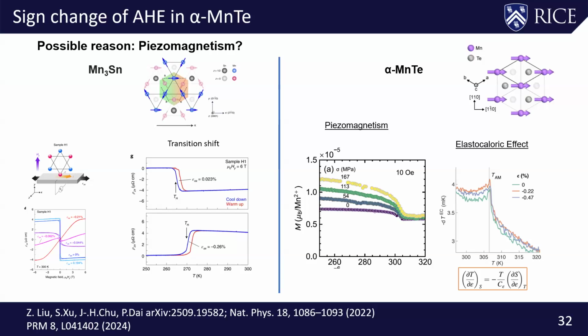Basically, due to the fact that you have a spin-lattice coupling, when you put a uniaxial pressure onto the system, you're changing the local symmetry, and therefore you change slightly the exchange coupling, and therefore you change the spin system. Therefore, the anomalous Hall is due purely to what we call piezomagnetism, because the magnetic structure changes slightly. Whereas in the case of alpha manganese tellurium, your piezomagnetism is 3 orders of magnitude smaller as compared with, for example, manganese tin. The amount of strain we can apply is like 0.1 or 0.2 percent of the system, and you can see the Néel temperature doesn't change, and this effect is much smaller, basically 3 orders of magnitude smaller.